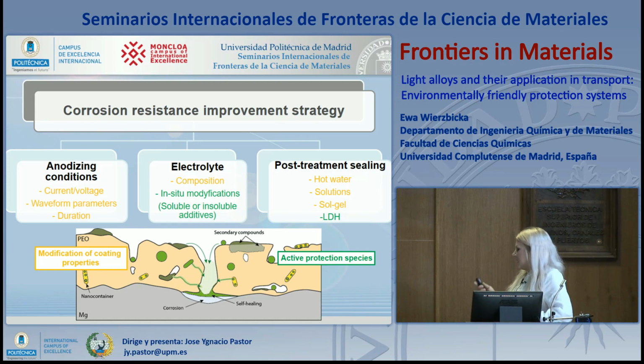by many options. First of all, we can change parameters that affect the basic part of the coatings, and for that we can change the anodic conditions, like current and voltage. We can change the waveform parameters and the duration of the process, the basic components of the electrolyte, or do some post-treatment sealing to reduce the porosity of these coatings. Second, we can improve long-term protection of our coatings by application of active protection species. We can use in situ modifications by adding a small amount of corrosion inhibitors into the electrolyte, as well as apply LDH as a post-treatment.